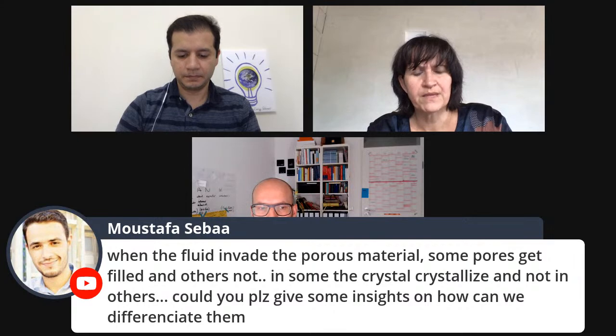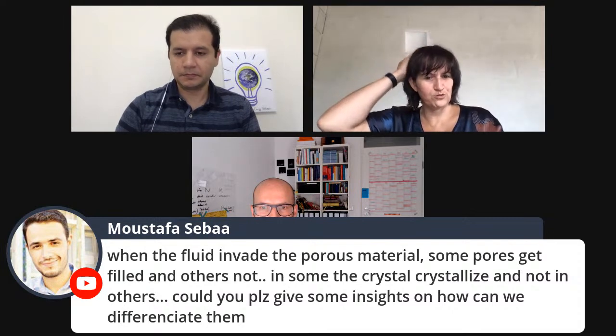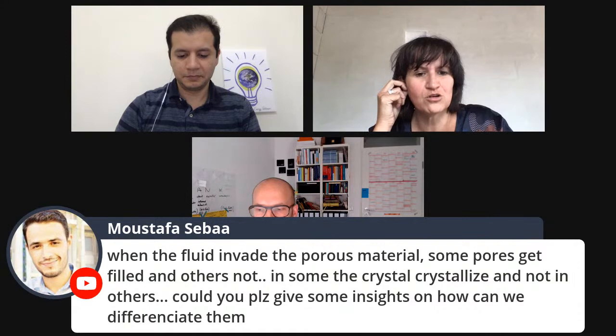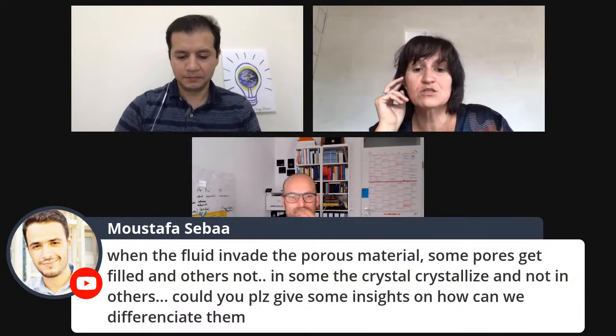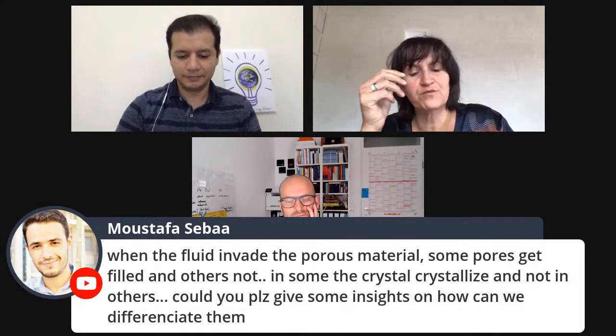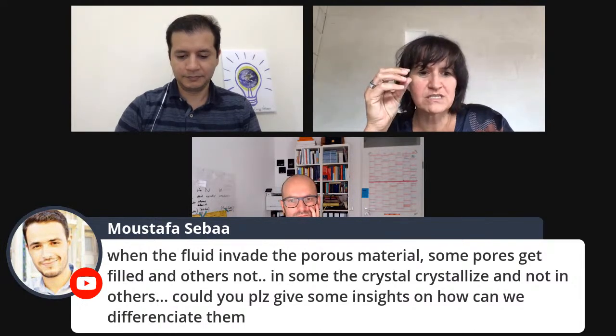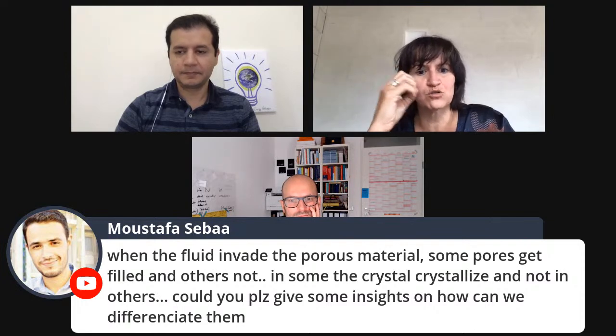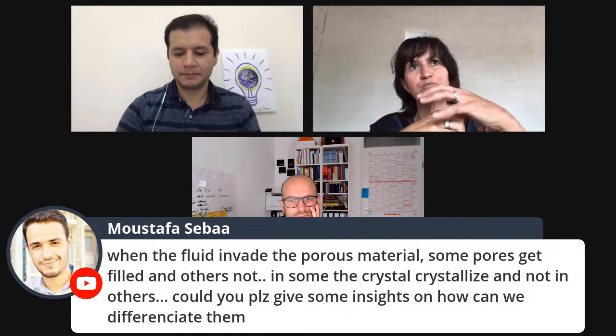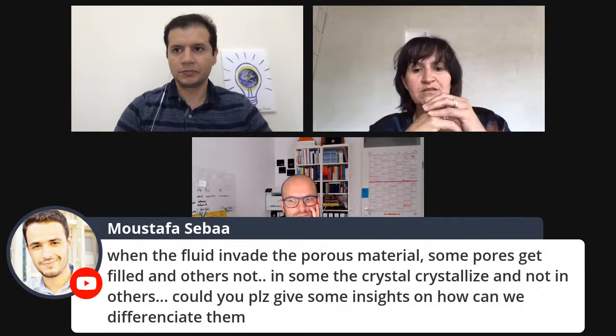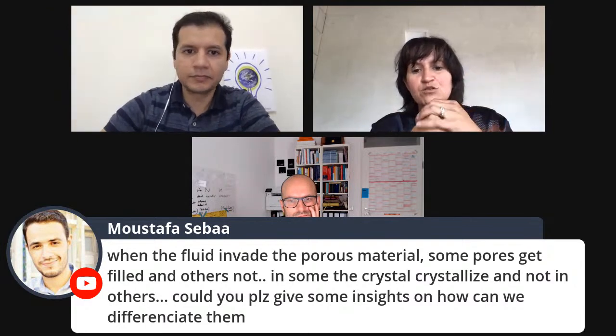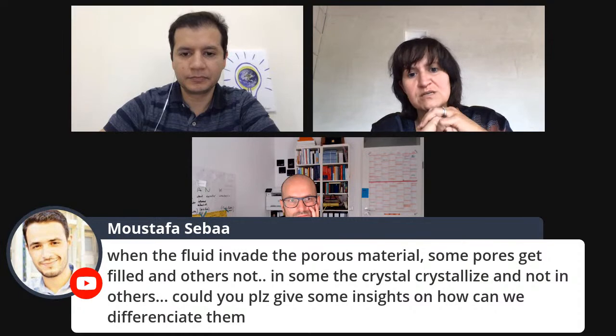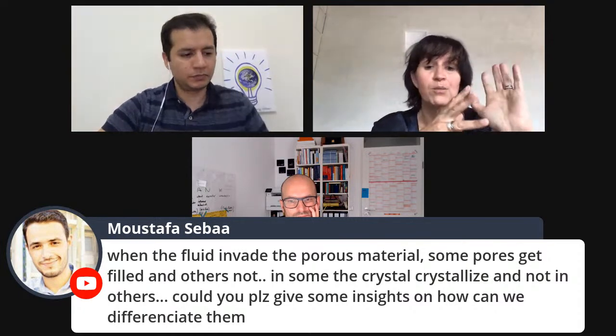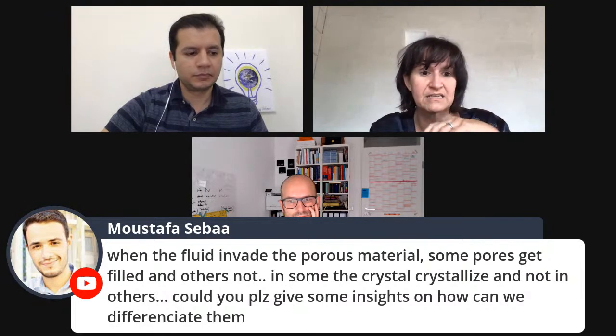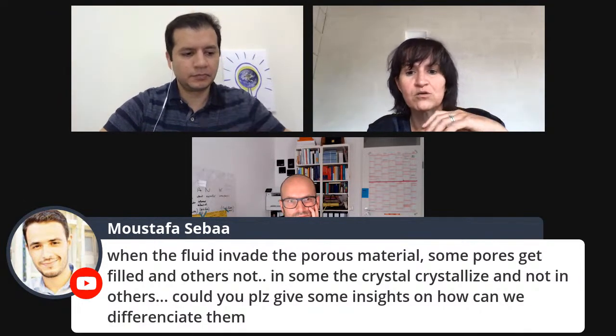Okay, because this is related to the pore structure, and this is also what you observe. So you first determine the pore structure, then you know where your fluid is going, and then you see. So we could quantify in which pores we get salt crystallization and how salt crystals were growing as a function of time, related to the pore structure and even the pore body. This helps you to have an idea where salt is precipitating, in which pores or which pore bodies or pore throats. So yes, you can quantify this, and this gives you insight into the growing of those crystals inside.